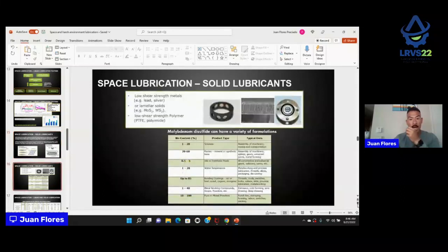lubricants. It is widely used right now, especially molybdenum sulfide, on some bearings, especially bearings with mid to low rotation speed. And it's a beautiful, beautiful microstructure. It's a microns to nanometer thickness, and the life is highly predictable. You can predict the life very, very easily.